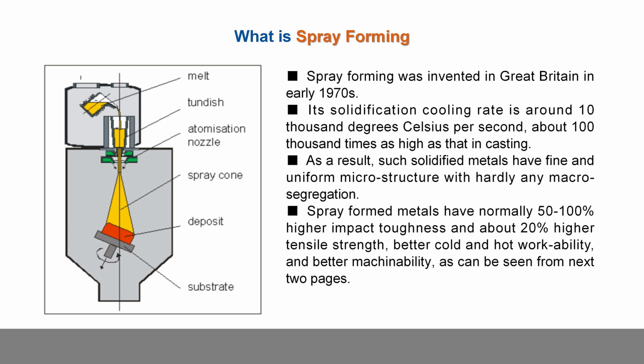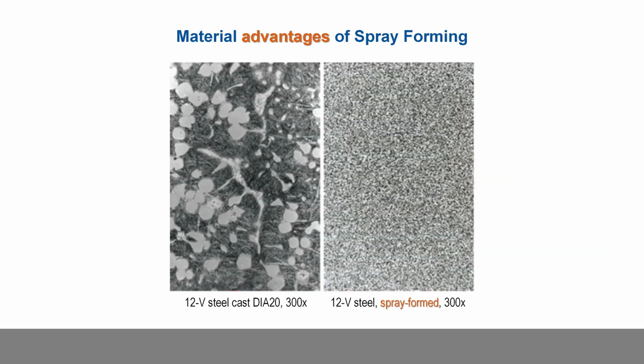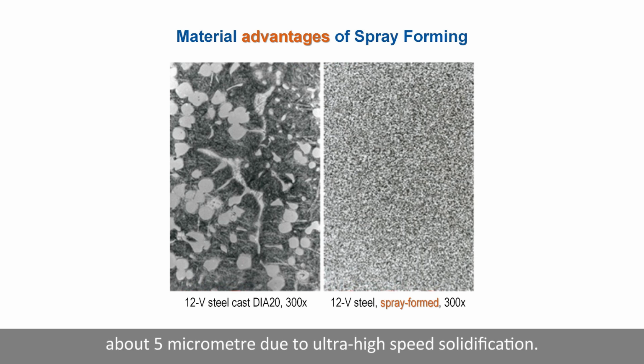Spray-formed metals normally have 50 to 100% higher impact toughness and about 20% higher tensile strength, better cold and hot workability, and better machinability, as can be seen from the next two pages. As seen in the microstructure comparison, the carbides in spray-forming steel were equiaxed, about 5 micrometers, due to ultra-high-speed solidification. The same features apply to aluminum, copper, superalloys, and other alloys.